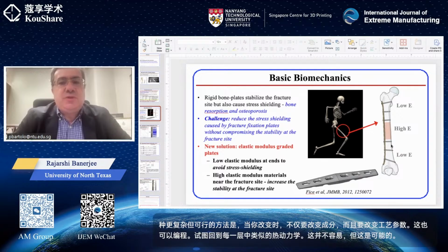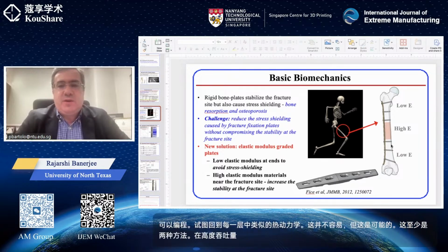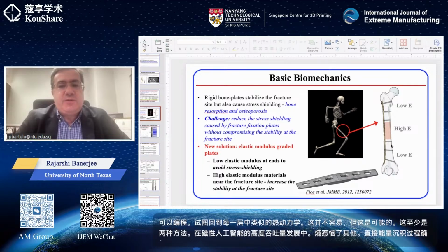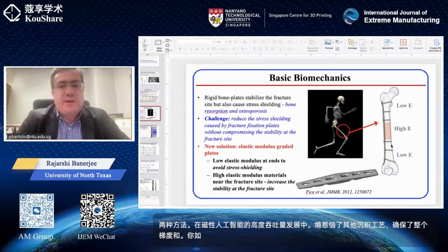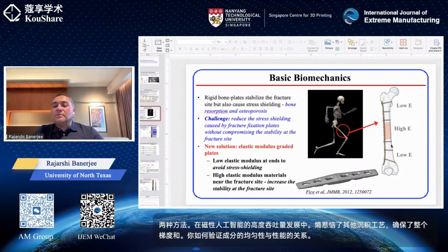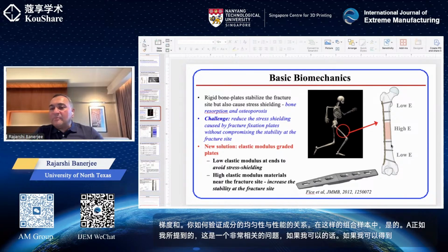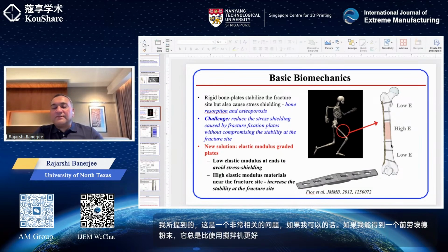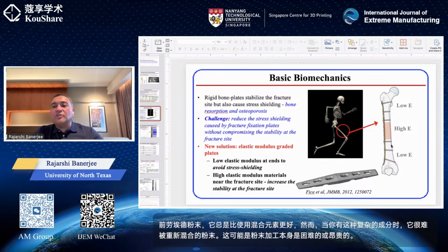In the high throughput development of magnetic high entropy alloys, how does the direct energy deposition process ensure compositional accuracy across the gradient, and how do you validate the uniformity of composition versus property relationship in such combinatorial samples? Yes, this is a very relevant question. As I mentioned, if I can get a pre-alloyed powder, it is always preferable over using a blended elemental approach. However, when you have these complex compositions, it is very difficult to get pre-alloyed powders. It could be the powder processing itself is difficult or prohibitively expensive. So using elemental blends is often the only way out.